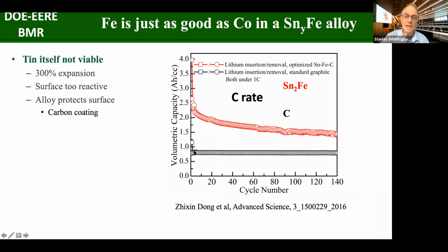And you can see the cycling behavior here is the black one is graphite. And you can see why people like it. It's absolutely stable for 1,000 or more cycles. But its capacity is only about 0.8 amp-hours per cc. Our tin iron material is more than double that, and even after 140 cycles, it's still double. So this is proof of principle that an alloy will work, will give us good behavior.